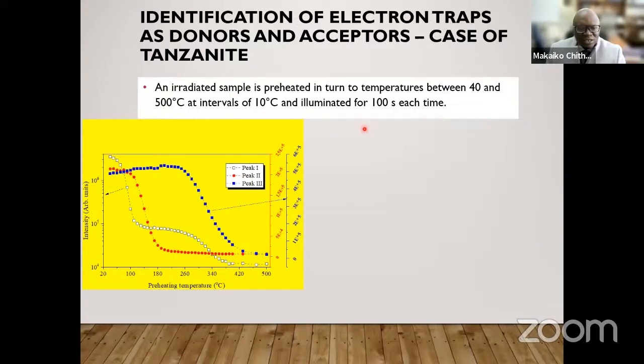So here is a result from tanzanite. The x-axis shows the preheating temperature. The y-axis shows the intensity. I've got plots here for peak 1, peak 2, and peak 3 that I showed earlier. We can see that peak 1 drops, becomes stable, then drops again. Peak 2, again, is a little bit stable to start with, then drops in intensity, then becomes more or less stable. Peak 3 grows in intensity, then decreases again.